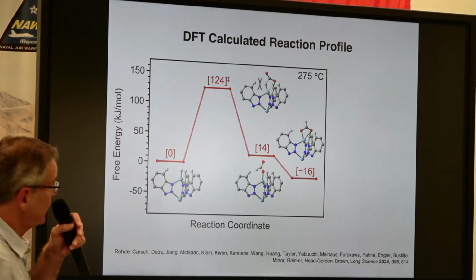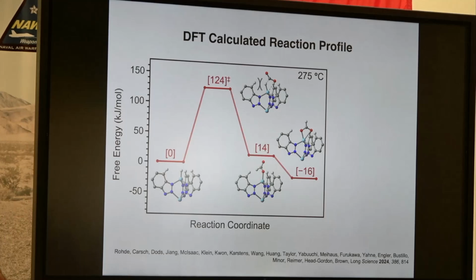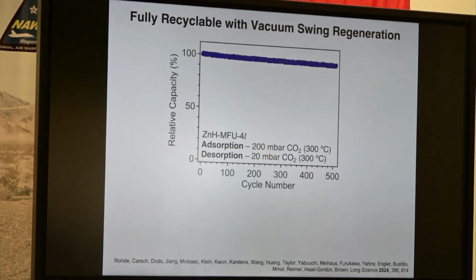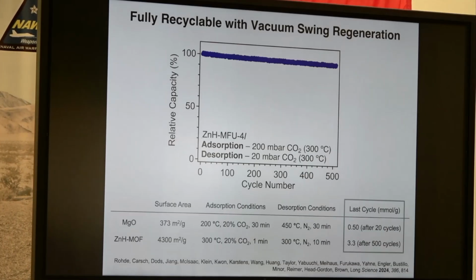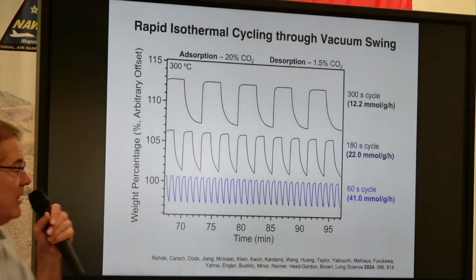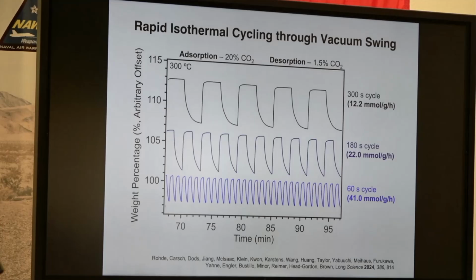And you can see in the transition state, the hydride is attacking the carbon and it's being pushed against the CH bond, creating that barrier. Okay, so now we can capture at these high temperatures and we can cycle without changing the temperature, just with a pressure swing. Right? This can be very fast. It's much better than you can do with magnesium oxide. You can cycle these so fast, you can do a 60-second cycle, adsorption and desorption, and get a large productivity for CO2 removal at 300 degrees C.